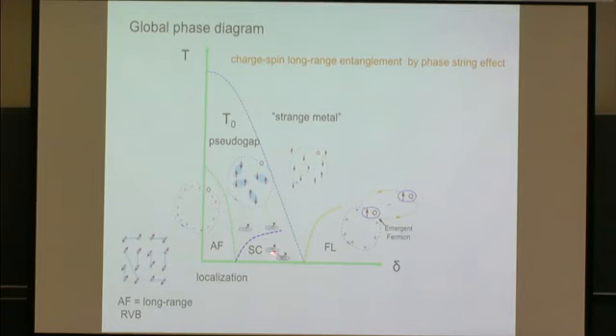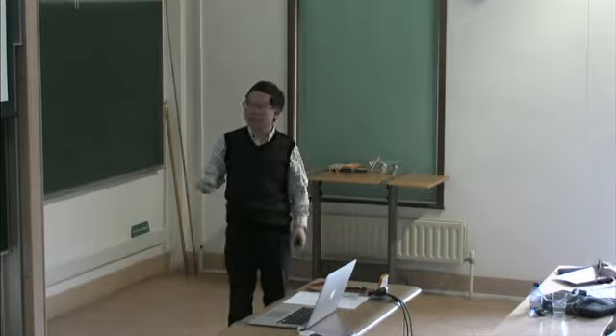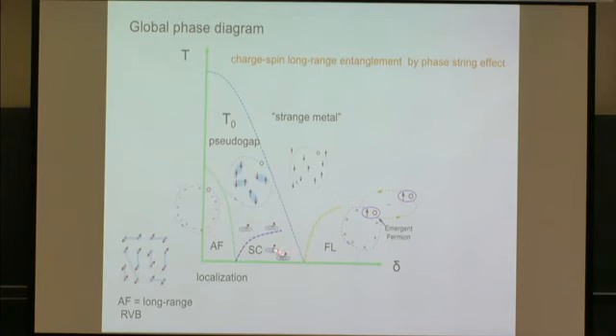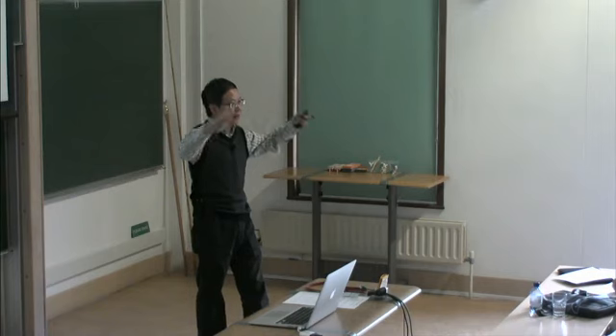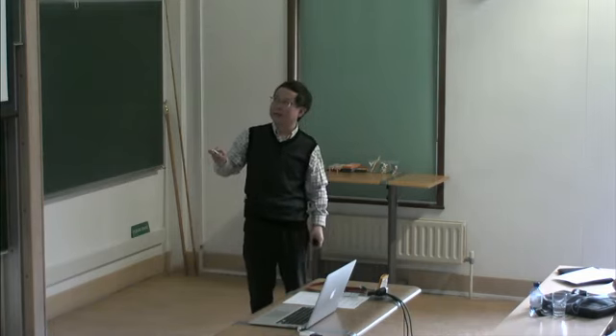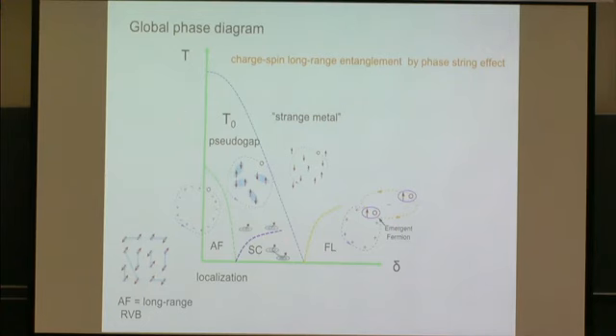Actually, the spinon is modulated, locked with some vortex to form a spinon vortex in the superconducting state to make sure of the phase coherence. So the transition is divided by vortex confinement and deconfinement, and then you have a zero gap behavior there.